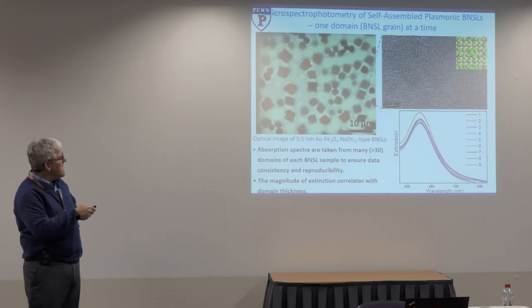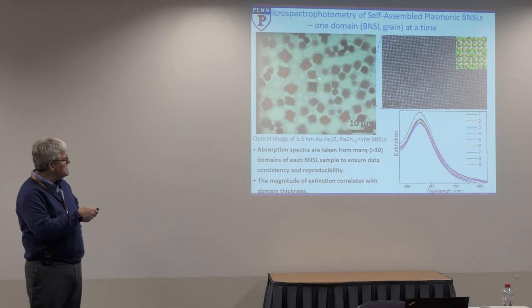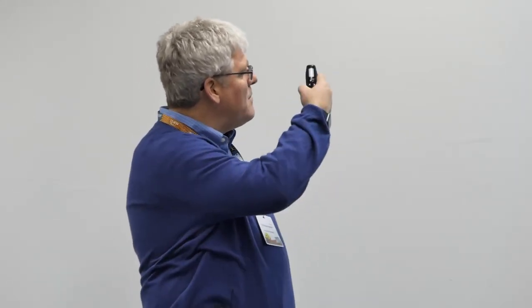But we can go in and do optical spectroscopy on each one of these, and because they have unique shapes and we can index them, we can do the optical spectroscopy on a box that's just a few microns, but then we can go in and do the electron microscopy, so we can do a one-to-one mapping. So this correlative microscopy is one of the things that is becoming increasingly important. The sequence is important, though. You can measure the optical properties and then do the electron microscopy afterwards, but you can't do the electron microscopy first because the electron beam is too damaging to the sample. It causes shifts, the deposition of carbon, other pieces. So the downside of this approach is you have to be patient.